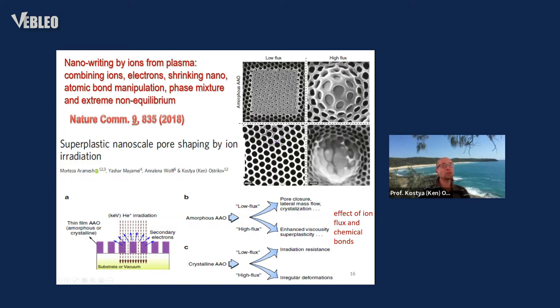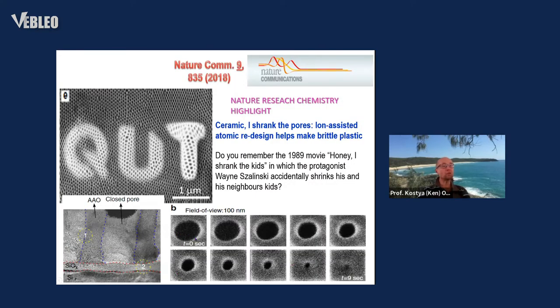And as you can see, this is the normal size of the pores, and this is the smaller size of the pore that could be reduced from typical, which is of the order of 100 nanometers, to just 10 nanometers or even below. This type of material swelling and shrinking the pores could actually be utilized as a very fundamental process of writing nanoscale features on the surface using these targeted and well-focused ion beams, where the logo of our university was successfully written and also published in this Nature Communications paper in 2018.